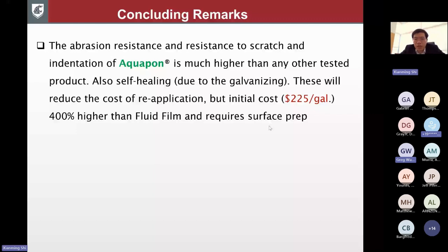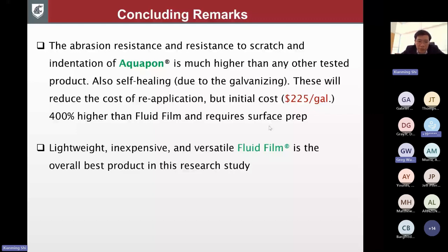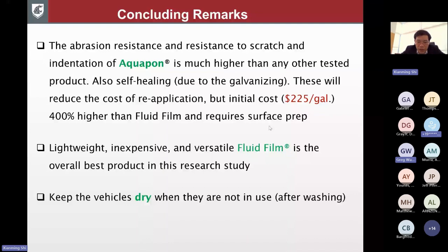Also, because it is zinc-rich, if you have a scratch, the zinc is supposed to pump electrons towards that defect, so it has self-healing properties. This can reduce the cost of reapplication, but this product has a higher initial cost, around $225 per gallon, about 400 times higher than fluid film. And because it's a traditional coating, it requires very rigorous surface preparation of the metal surface. On the other hand, fluid film is lightweight, inexpensive, versatile, and doesn't require very rigorous surface preparation of the metal. One lesson learned is also to keep the vehicles dry when they're not in use, after they've been washed and there's no residual salt. That could extend the service life of the equipment assets.